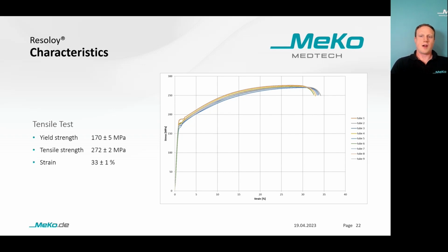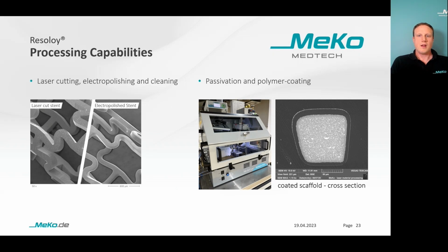The extraordinarily high strain with a relatively high ultimate tensile strength makes Resoloy suitable for use as a coronary scaffold, for example. Due to the deformation during crimping and expansion, a high strain is required. The ultimate tensile strength would result in a high radial force of a scaffold or stent. In the following slides, I will show the processing, post-processing, and test capabilities of MeKo.